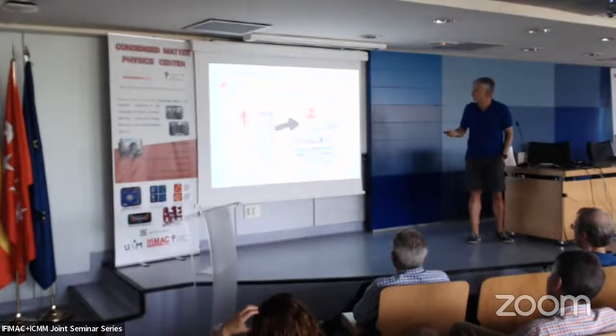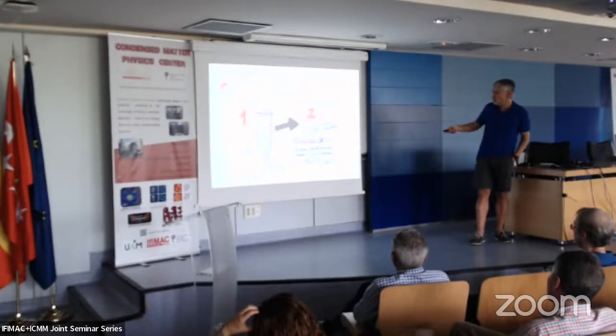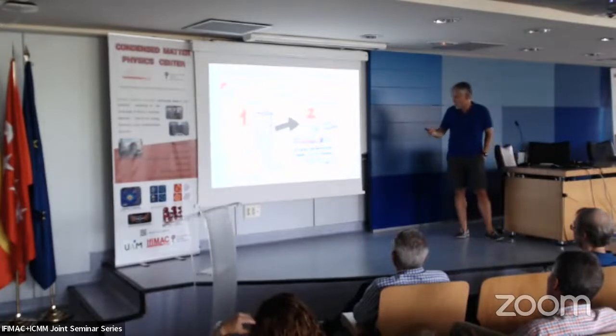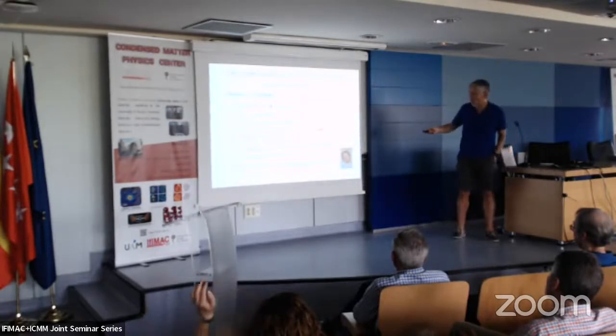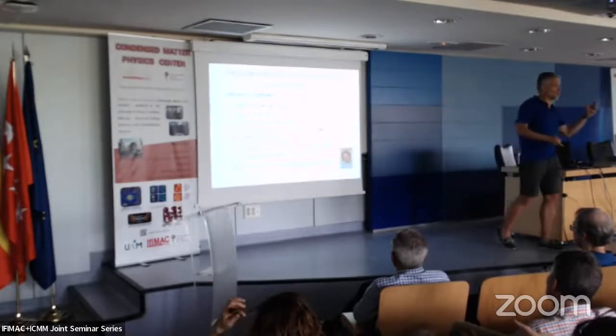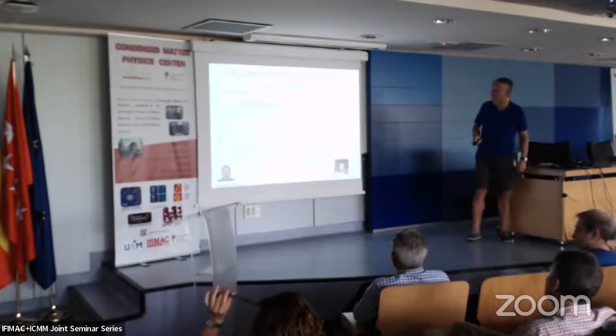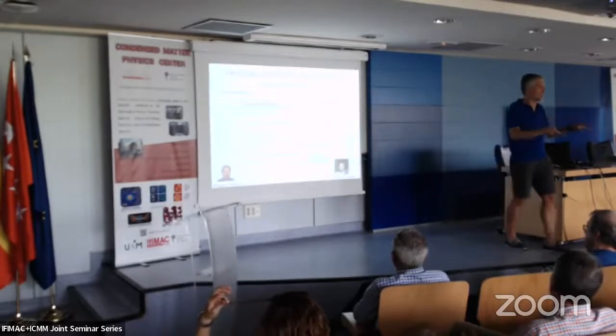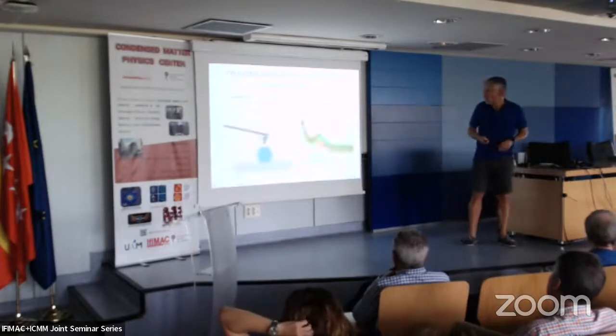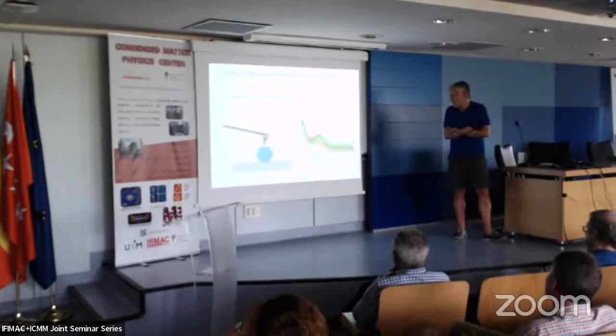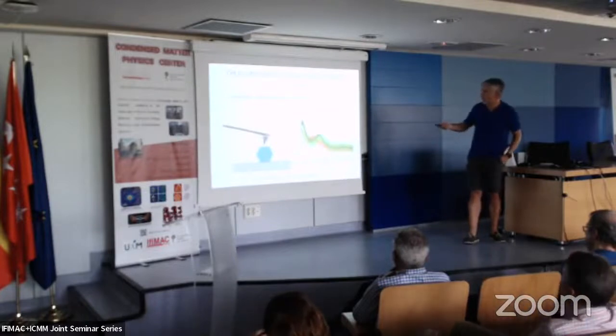The second approach, in the project IFIMAC, is to try to understand the trapping of viruses on the surface. We are now trying to understand this by following the Langmuir isotherm to extract the information about what is the equilibrium constant of viruses trapped on the surfaces. Okay? And these are the first experimental results we obtained, for instance, with human adenovirus and also with coronavirus in this case. So we are trying to check the difference between different materials, such as HOPG, or mica, or glass, etc.